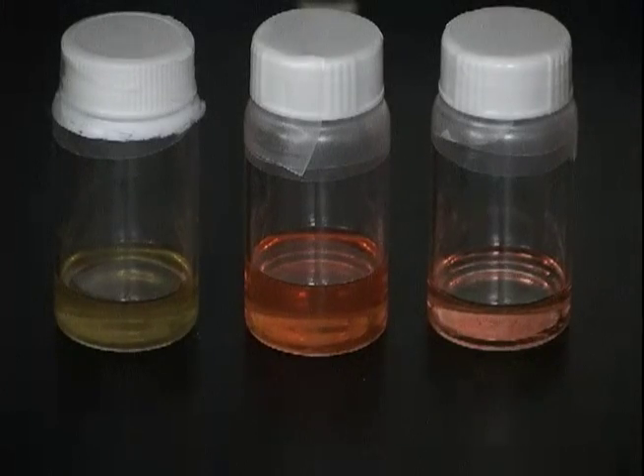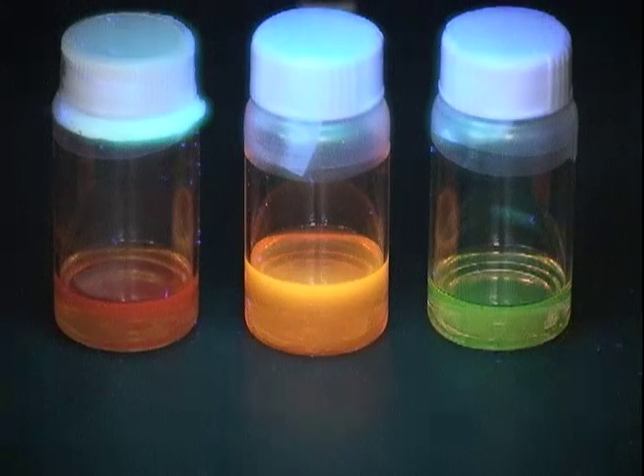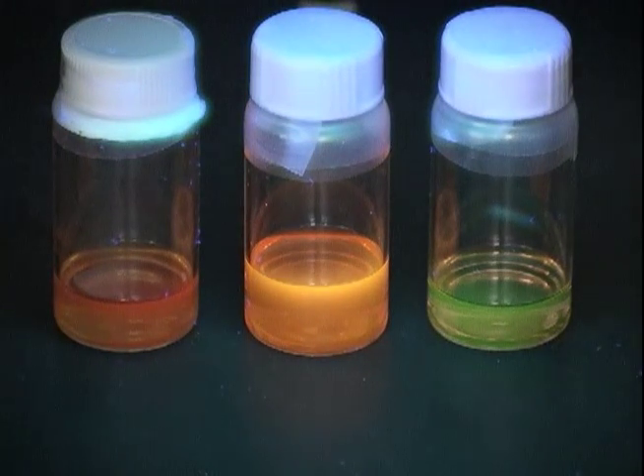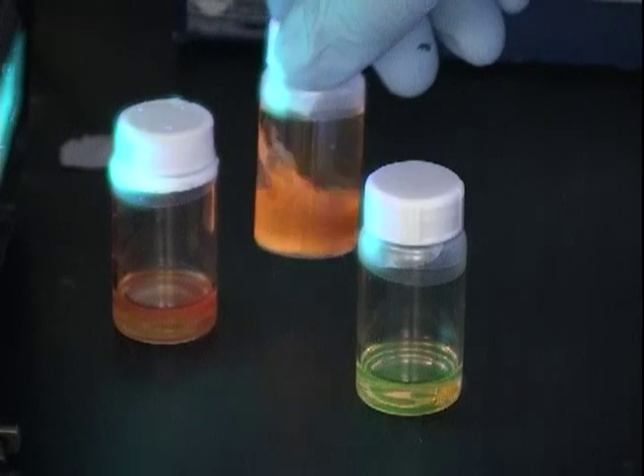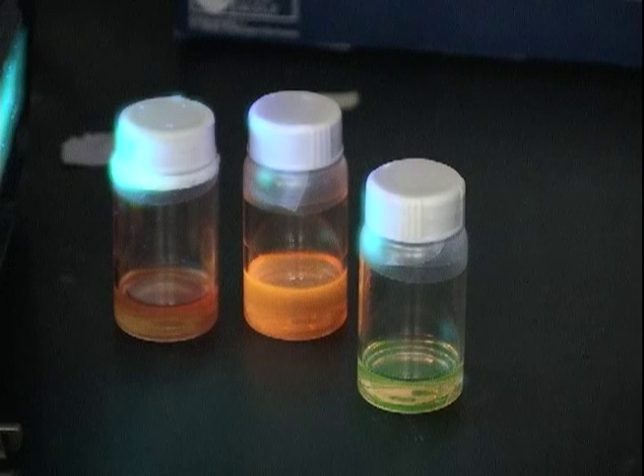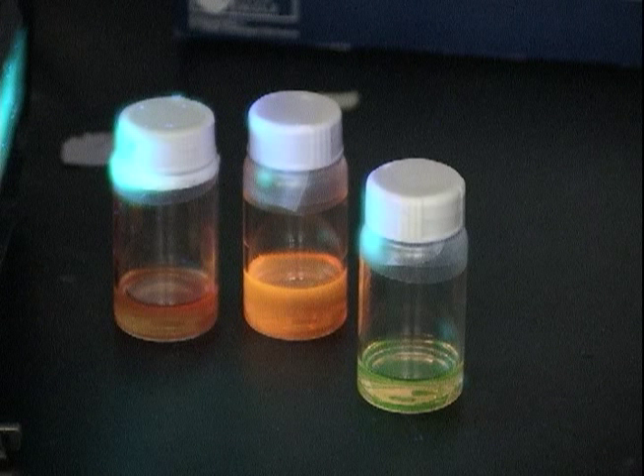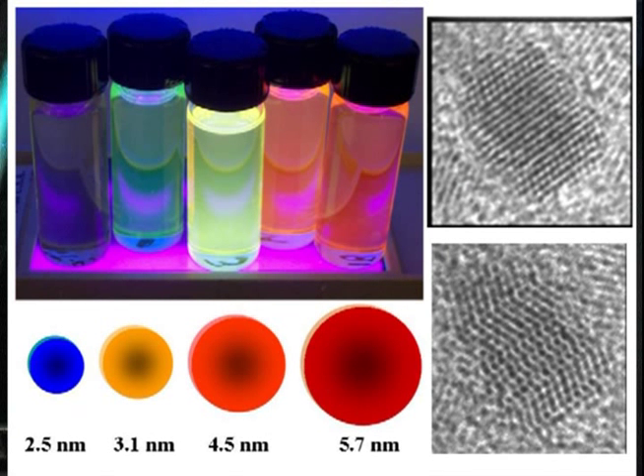This is a sample of finished nanoparticles of three various sizes. You can see under room light they're very close in color, but as we illuminate with a UV lamp you can see the effect of quantum confinement — a change in emission color based on size. The appeal of using these nanoparticles in photovoltaics or especially in LEDs is that they have a very narrow emission, giving LEDs very pure light. They also have a size-tunable emission, so once you can solution-process one, you can change the color of your LED without changing your processing options.